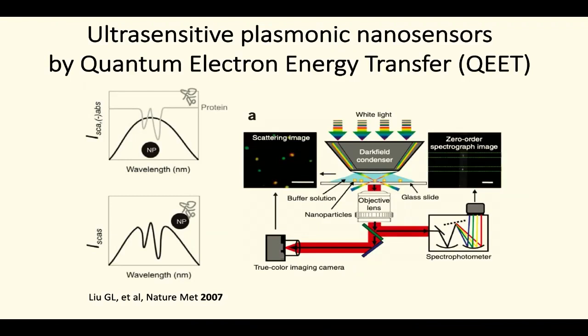So this is a typical image of gold nanoparticles on a dark field microscope. The dark field microscope shines light on a sample while preventing the light of the source from arriving at the detector. So what you actually measure in the dark field microscope is only the scattered light. If you shine light on gold nanoparticles, part of the light is absorbed and part is scattered, so that's what you observe. That's why we observe different colors from the nanostructures in the microscopic image, because depending on the size of the nanoparticle, you get scattered light with different wavelengths. That's normal plasmonics and scattered light. This system is around 200,000 to 300,000 euros.